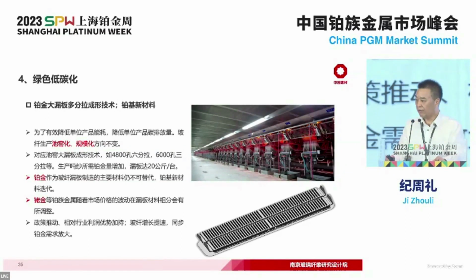Under the backdrop of a low carbon economy, PGM will enjoy strong demand, because if we are to reduce emissions and improve energy efficiency, then the bushing will be much bigger and have more holes. In this structure, PGM will be used more. Also, we are looking at the possibility of reinventing or evolving the application of PGM in the bushing. As for rhodium, our point of view is that its demand will fluctuate according to its own price. If the rhodium price is less than 500,000 RMB, then the industry will again buy rhodium, because rhodium does enhance the performance of the bushing. The alloy of platinum and rhodium will generate the best performance, which is a consensus of the industry.